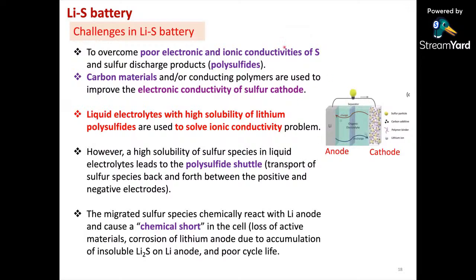Okay. So what are the challenges? Sulfur has poor electrical conductivity, electronic conductivity. So in order to enhance the electrical conductivity, one can add carbon additives. What we have done is that we have used 1D, 2D carbon nanomaterials as an additive. And this has poor ionic conductivity also. So what we have to do is use a liquid electrolyte with high solubility of lithium polysulfides, because lower order lithium polysulfides will be formed, and finally you tend to get the Li2S.